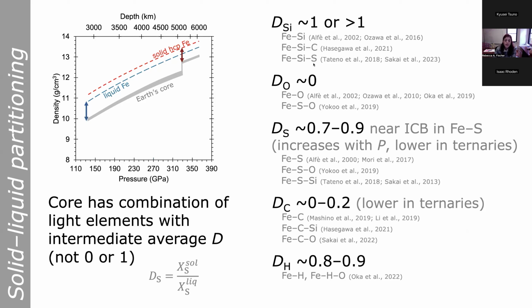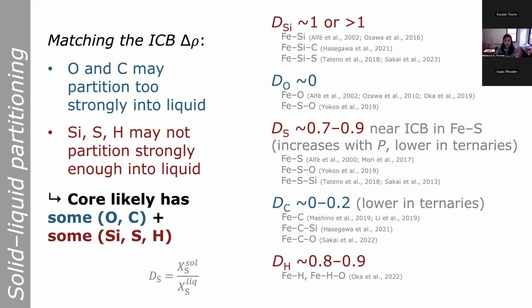in the inner core. So if we look at all of these candidate light elements, this is sort of a rough summary from a bunch of different studies looking at various binary and ternary systems involving these elements. And what you'll notice is that oxygen and carbon in blue have partition coefficients very close to 0. They partition very strongly into the liquid, too strongly to be able to explain the inner core's density, perhaps. On the other hand, silicon, sulfur, and hydrogen in red all have Ds close to 1, especially silicon, whose D can even be above 1. So they may not partition strongly enough into the liquid.